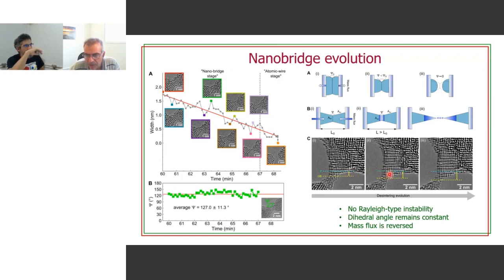You can count how many atomic planes are within the bridge as you move the two nanoparticles apart, and you reach the conclusion that in fact you are adding more and more atomic planes so that you can keep this dihedral angle constant until the system breaks. So these are the take-home messages. There's no Rayleigh-type instability. The dihedral angle remains constant, as I said, and the mass flux is reversed.